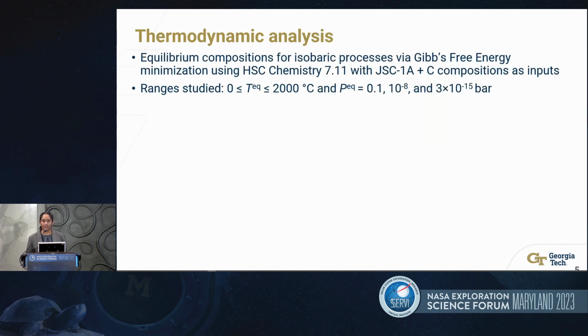We conducted thermodynamic analysis in which we obtained equilibrium compositions for isobaric processes via Gibbs free energy minimization. The HSC Chemistry software package was used, and the mixed sample compositions were the inputs. The temperature range studied was from 0 to 2000 degrees Celsius, and at three different pressures: 0.1 bar, 10^-8 bar, and lunar surface pressure.